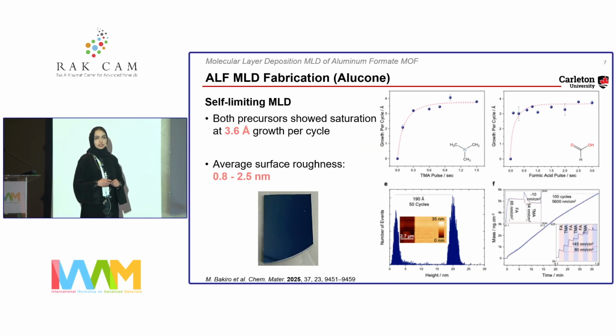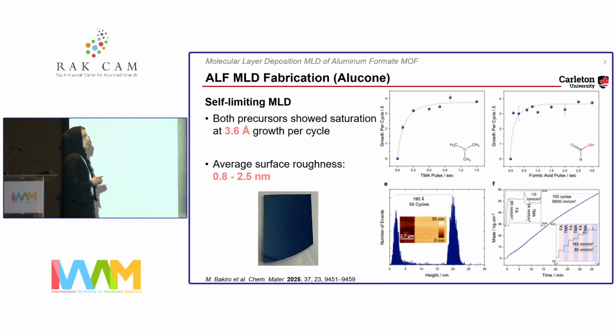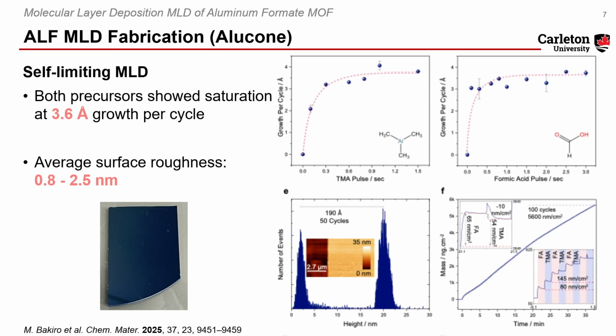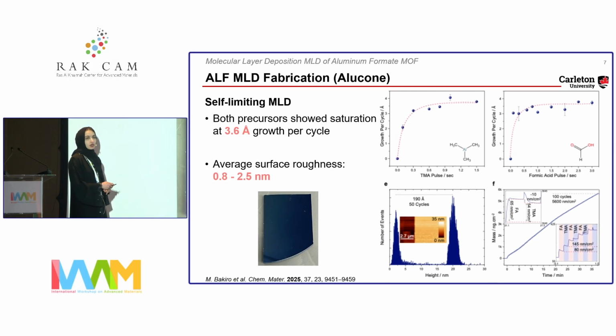And in MLD, molecular layer deposition, in order to know how much material you should deliver to the surface, so it's not too little, it's not too much, you have to generate what's called the saturation curves, which are the two curves you see here. On the y-axis, you see the growth per cycle, that's the thickness per cycle, and here is the dosage of the precursor. In this recipe, you have two precursors, formic acid and TMA.